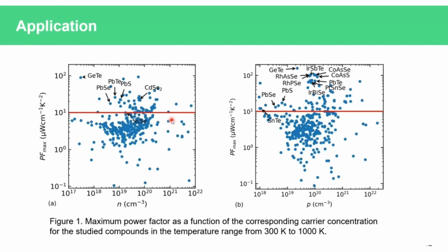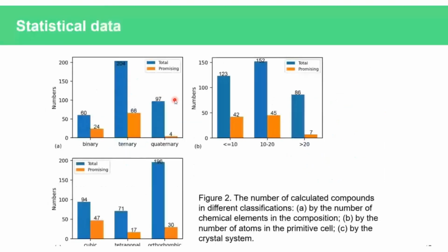Some representative compounds are also marked in the picture. Among these compounds, 6 of them, including germanium telluride, tin selenide, lead telluride, lead sulfide, are already well-known thermoelectric materials and have high power factor according to our calculation, which validates our method.